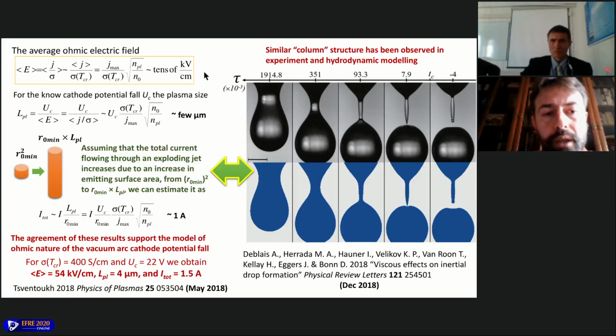And all the cathode fall, which is about tens, maybe 20 volts, can be provided within this explosive plasma in a few microns. So this electric field can provide all the cathode fall within a few micrometers. It corresponds to observation of small-scale plasma, and it corresponds to the known cathode fall.